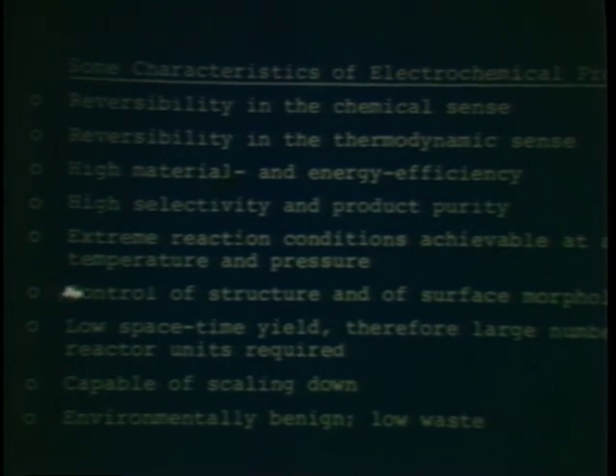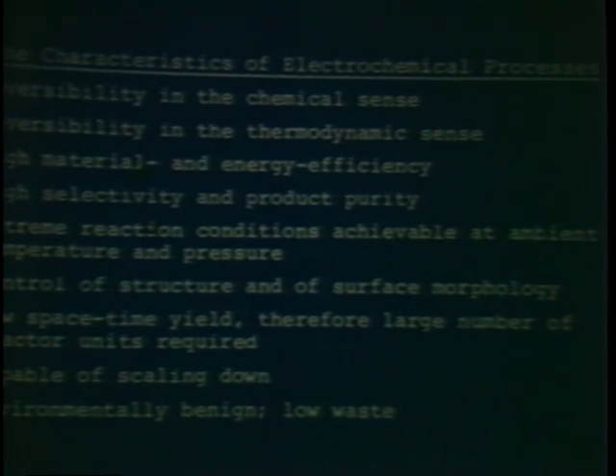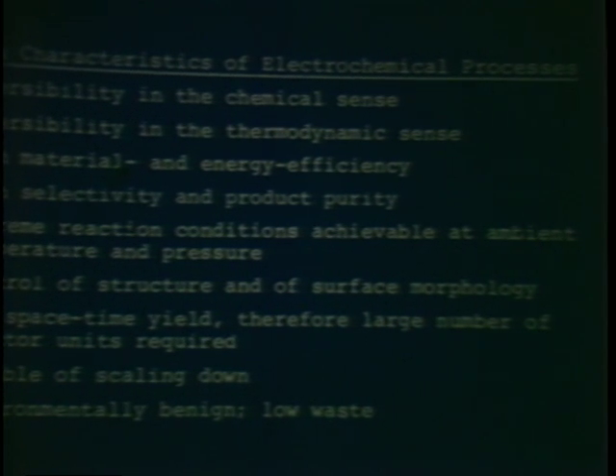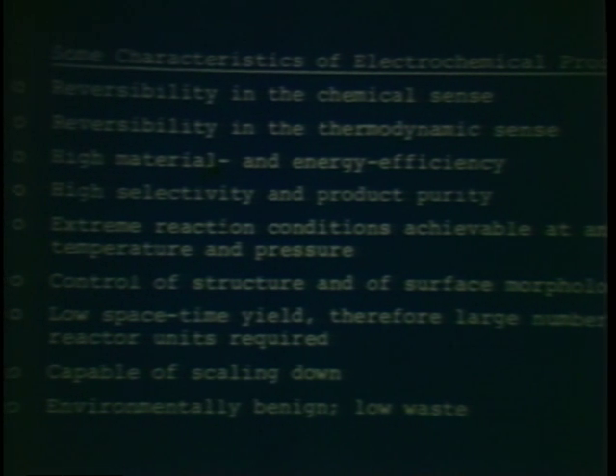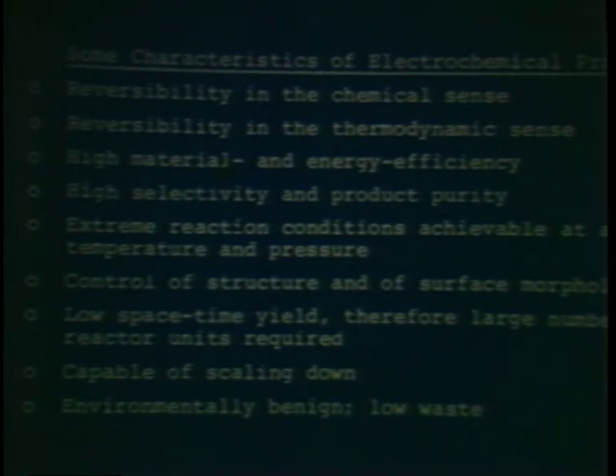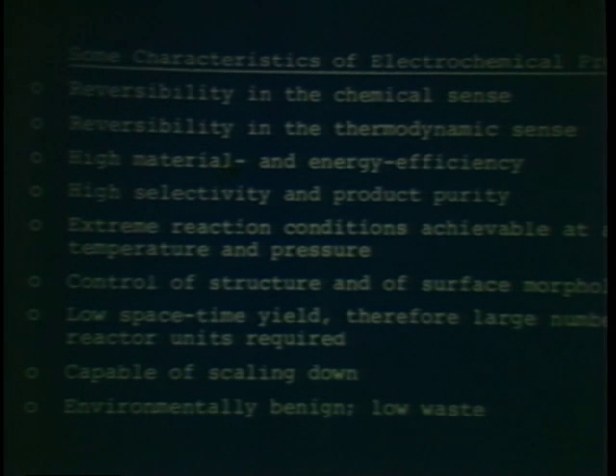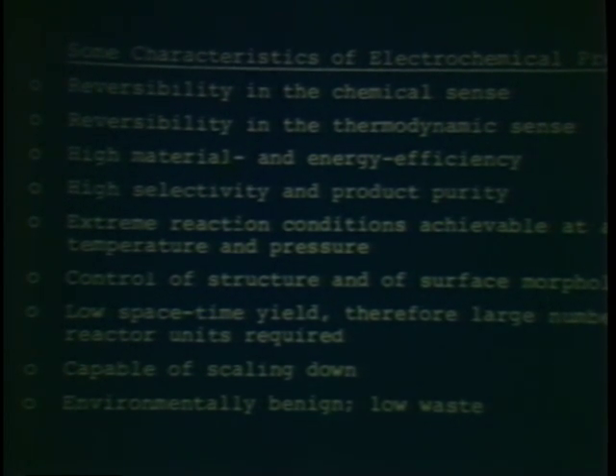One terribly interesting feature of electrochemical transformations is that it is not only suitable for producing a bulk chemical, but within a single reaction step, it may yield a product, a metal, for instance, or an alloy with a predetermined structure and surface finish. It may be a metal that is deposited with a mirror bright finish and a very thin layer.